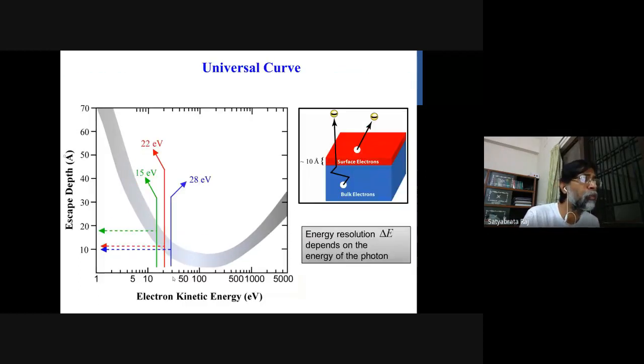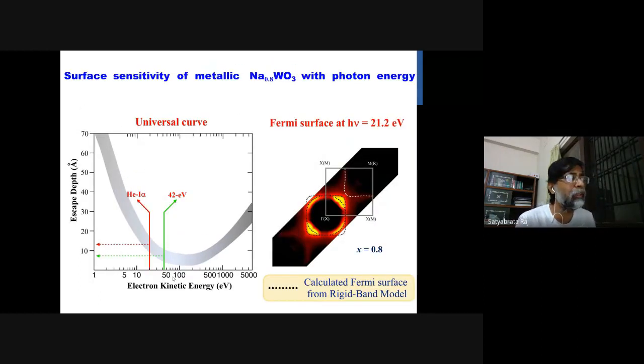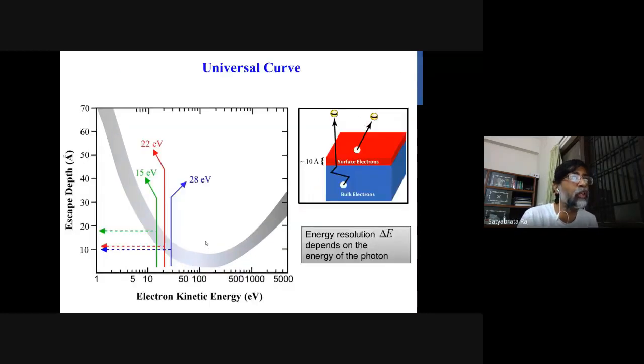So based on that one, we have measured this Fermi surface in various photon energy, starting from the 21, which is the helium 1 alpha line in the laboratory energy, which is coming from the helium source. And in the synchrotron, we have measured up to 42. 42 is actually surface sensitive. So let's see how it looks like.